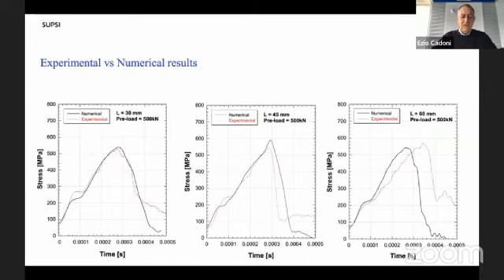Here is the comparison between the stress versus time curve obtained experimentally and numerically for the 3 dimensions of samples. The good agreement between the experimental and numerical results is due to the fact that the DAMP material model evaluates the interaction between damage propagation, loading wave, and specimen size.